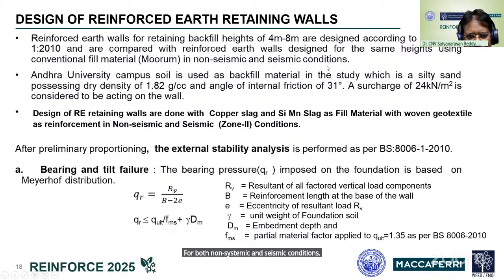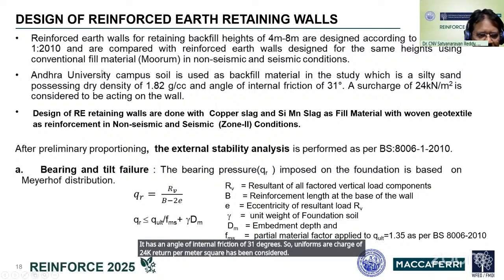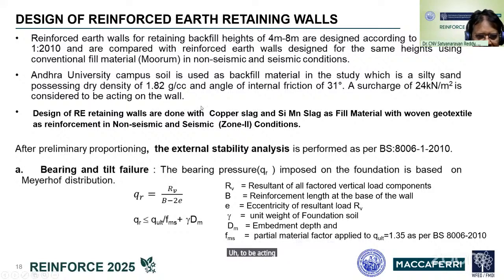The backfill material considered in the study was the locally available soil at Andhra University, that is silty sand, which has a dry density of 1.82 gram per cc. Saturated density, if you find, will be around 2.1 gram per cc, taking specific gravity as 2.66. It has an angle of internal friction of 31 degrees. A uniform surcharge of 24 kilonewton per meter square has been considered to be acting on the wall for design.